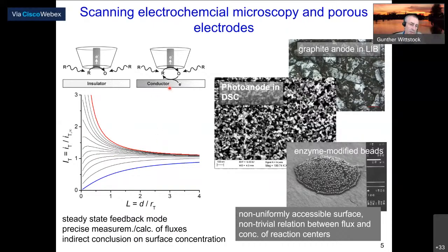However, if the surface is a conducting surface, then we can establish a feedback loop where the mediator is oxidized at the microelectrode and the backward reaction happens at the sample. And now there are two sources for the reactant to the microelectrode. It can come from the sample in this recycling loop, or it can come from the solution. And therefore, the current goes up when we come closer to the surface, because then the recycling loop becomes more and more effective, and you see that as the red curve.